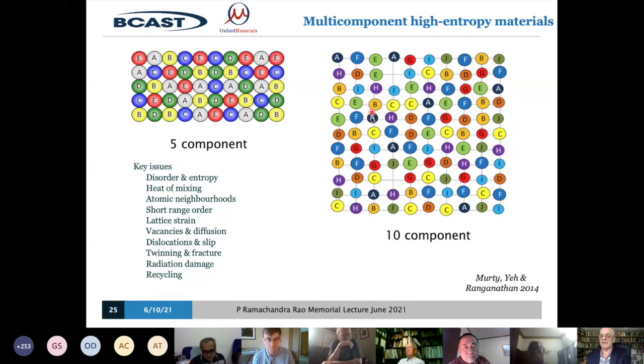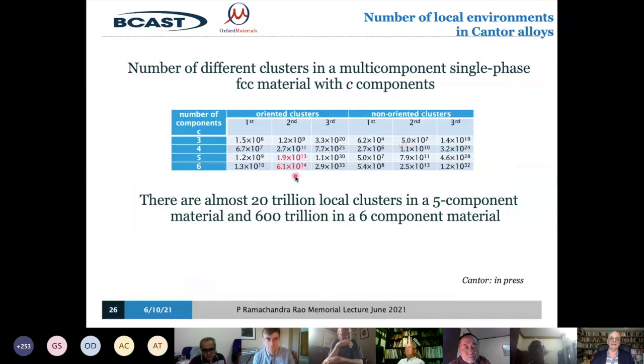Well, let's look at how many local environments there are first. If you do the combinatorial maths again, it turns out for a five-component alloy like the original Cantor alloy, thinking of first and second near neighbors, there are 20 trillion different local environments. If you have a six-component material, there are 600 trillion different environments. If you include third near neighbors, which sometimes have an impact on the properties of a material, you get to crazy numbers like 10 to the 30 and 10 to the 33. In other words, you need an enormous chunk of material to even give yourself a representative sample. Two chunks of material are different because you can't have all that number of local environments unless the material is a very large piece.